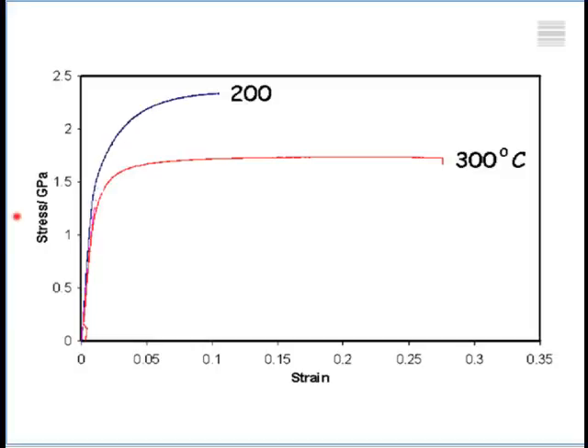Now, let me show you, since this lecture is about strength and toughness, and ductility is vaguely related to toughness, here you can see the ductility and the strength. So here we have an elongation of 27% when I formed that structure by transforming at 300 degrees centigrade and approximately 11% when we transform at 200 degrees centigrade. But the tensile tests themselves are at room temperature.